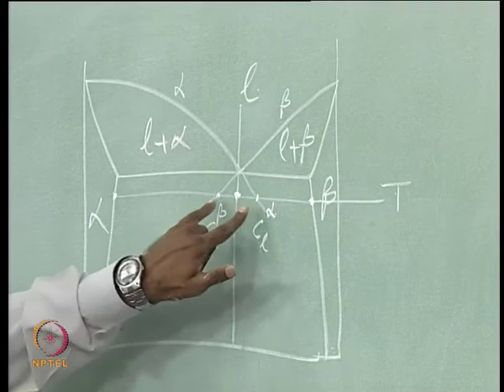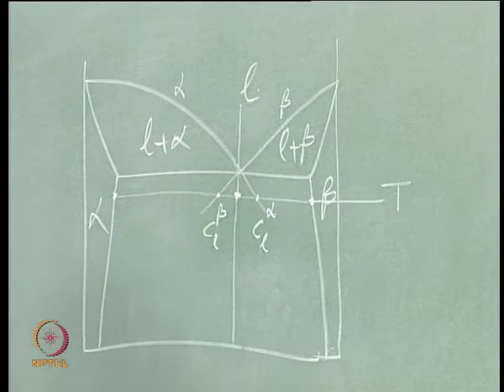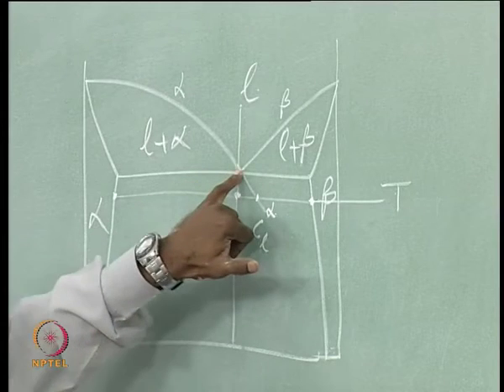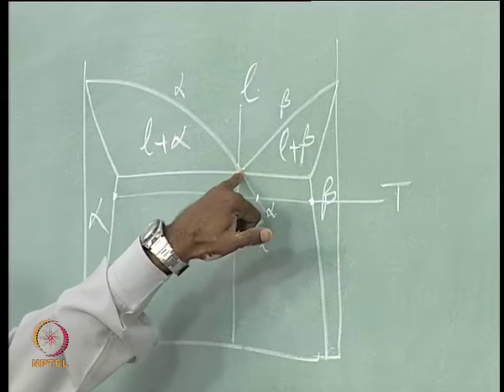The difference between these two is actually the driving force for the growth of eutectic. If you want the eutectic to grow, that is the reason why, if you carefully observe, at the eutectic temperature this difference is 0.